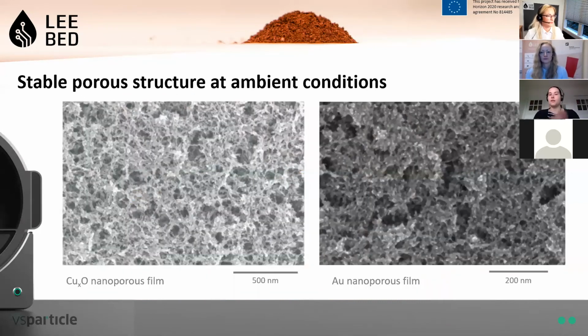So this is what such a line, a gold line, for instance, on the right-hand side looks like under an electron microscope. You see that the printed structure is very porous. It's a very open structure, and the primary particles are really small. As I mentioned, they are sub 20 nanometers. The morphology is quite independent of the material. On the left-hand side, you see an example of a copper oxide film. It looks quite similar to the gold nanoporous film on the right-hand side. And these porous structures are stable at ambient conditions, at ambient temperature and pressure.